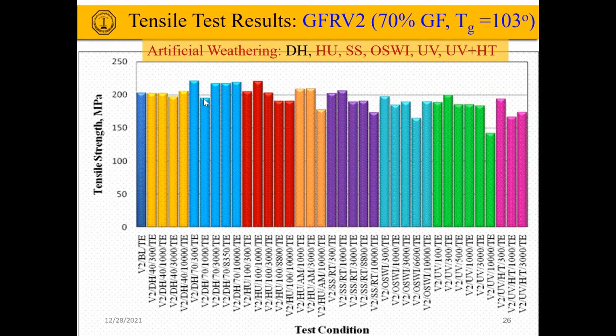You can see that dry heat does not affect negatively the tensile strength. Actually, at 70 degrees, it seems like it is curing the material more and it's increasing its tensile strength. But humidity, salt spray, UV, salt water, etc., tend to reduce the tensile strength of GFR-V2.